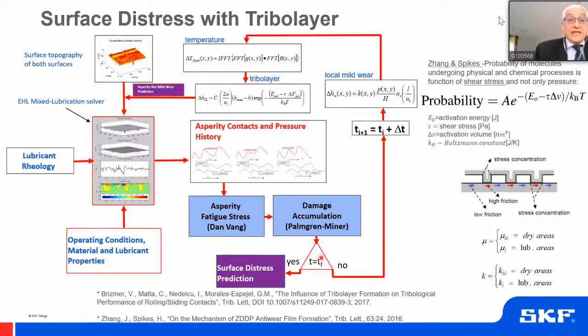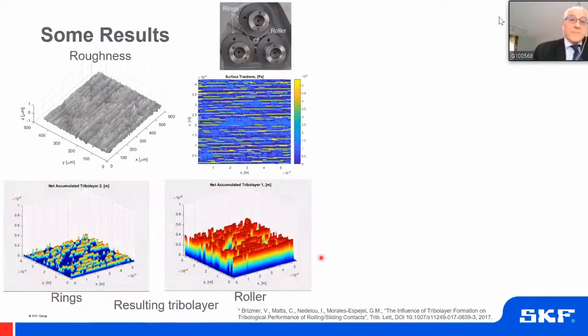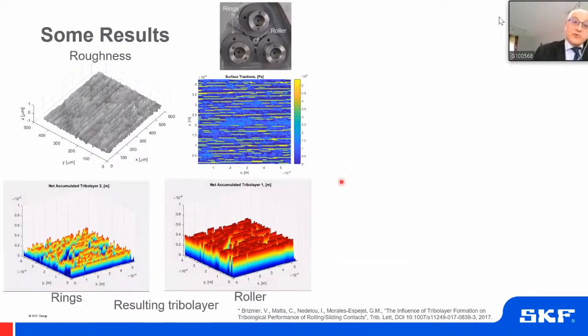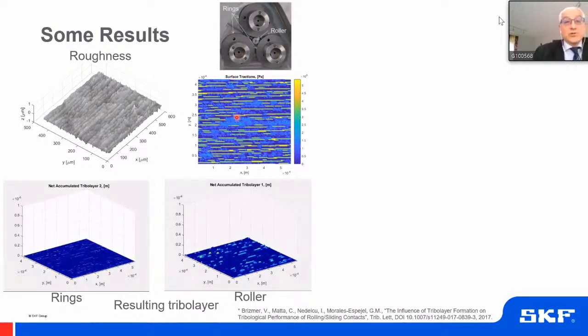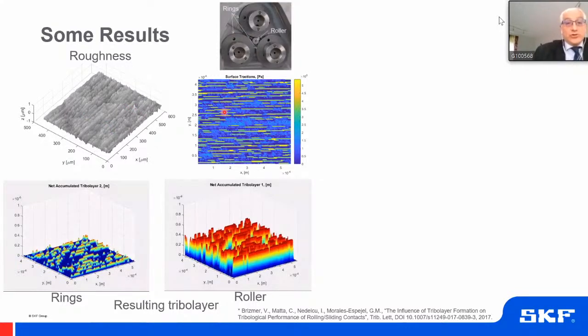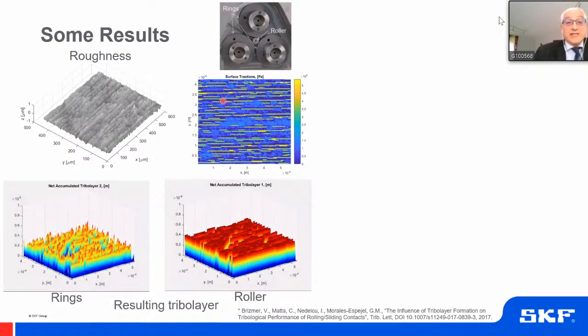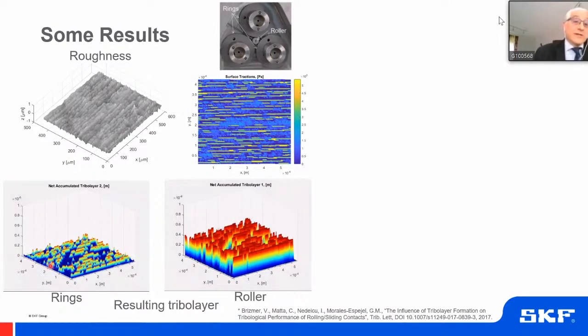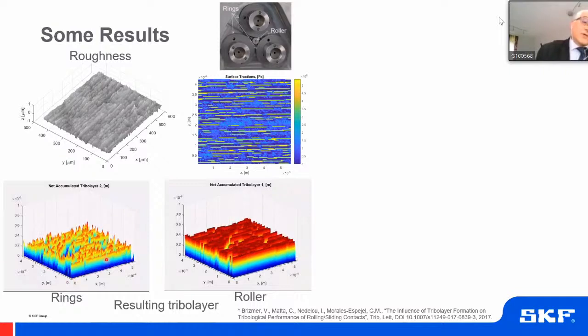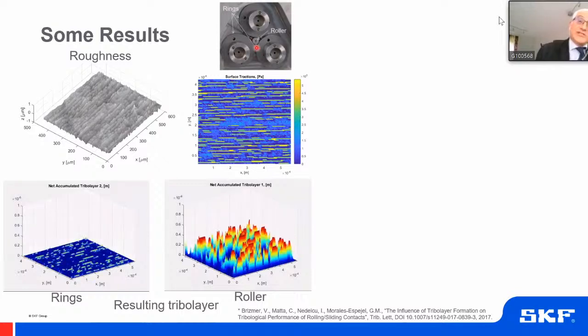And interestingly, at the end of the day, we can basically simulate things like what we see in the experiments. Again, our tester here, this is a topography we started with. This is just a very short snapshot in time of the shear stresses at the surface calculated by the model. And then you can see how the tribofilm is being grown on the rings and on the roller. And it's much faster on the roller because it sees many more cycles.